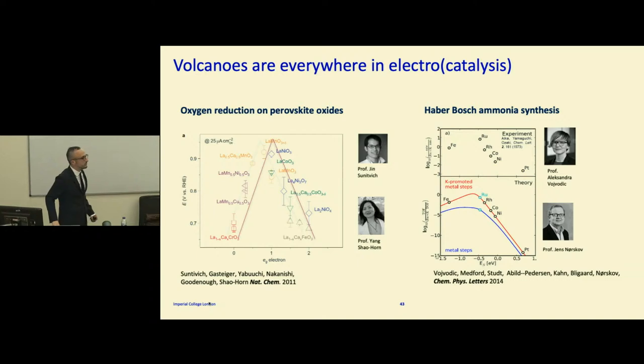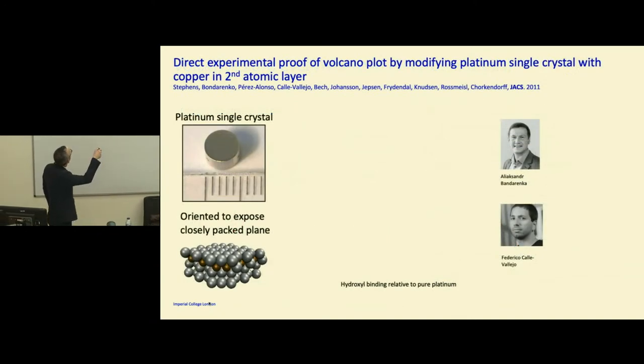So one of the nice things we had at DTU was the ability to work with single crystals. Essentially, you can take a macroscopic crystal that has been oriented to expose almost entirely one crystal facet. So this is a closely packed plane of platinum. You can see all the balls closely packed together. And I was working with Alexander Bandarenko, a really good team in the lab, in our very rudimentary lab, actually.